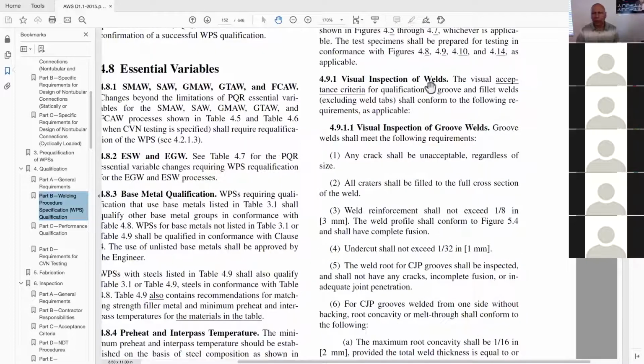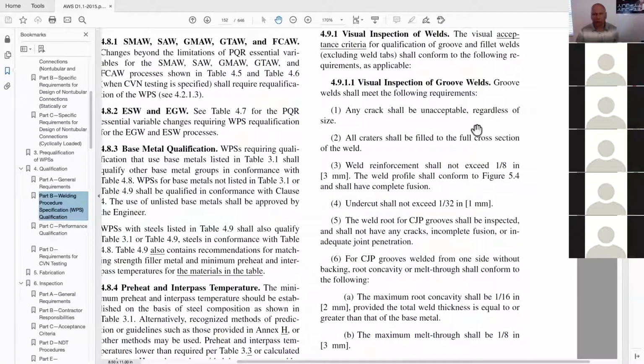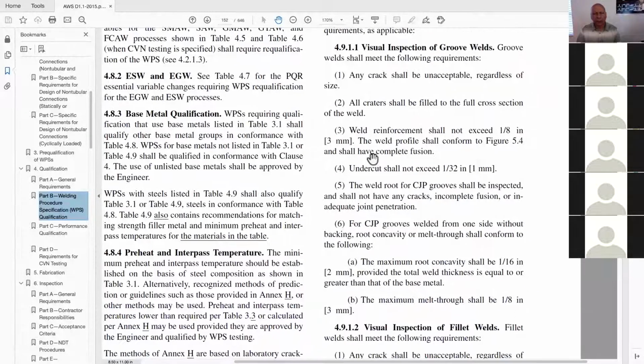We do a visual inspection on that weld test coupon right here in 4.9.1.1. And so you check for cracks. I've never in my life seen a crack on a test coupon, unless it was a very large test coupon and we were qualifying a WPS. If we're qualifying a welder, a crack is totally unusual. But craters are sometimes there, and they leave underfill, and those have to be filled to the full cross section of the weld so that it can be determined when doing a visual inspection. The weld reinforcement shall not exceed 1/8 of an inch, and the weld profile shall conform to 5.4. Well, we use a gauge, and it's pretty easy to tell. If it exceeds 1/8 inch, the welder fails.